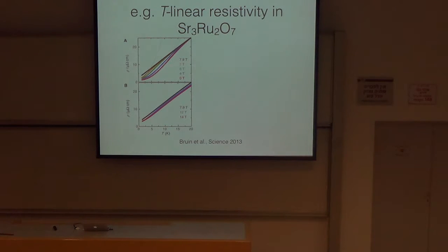I'll get to a little bit of that in a minute. But the basic idea is that you can plot this data, taking the exponent of the T-squared to T-linear resistivity as a function of field, and you can plot it as this color plot. I'll be showing you a couple of these plots in the next few slides, so it's useful to get familiar with it. But what it basically shows is that you can have a crossover from T-squared resistivity to T-linear resistivity back to T-squared as you tune the magnetic field.